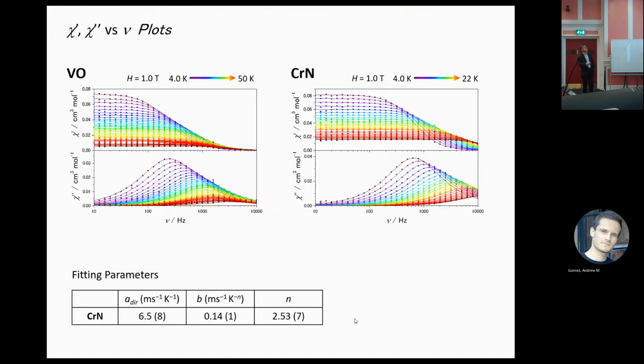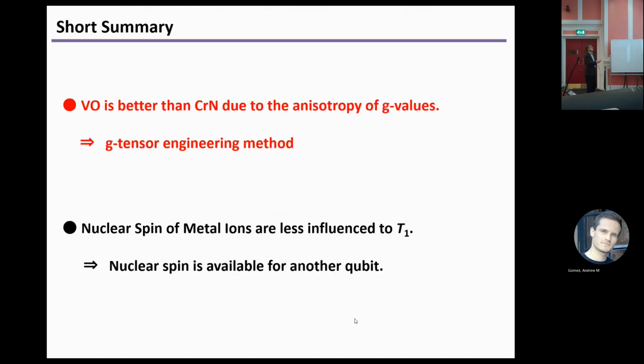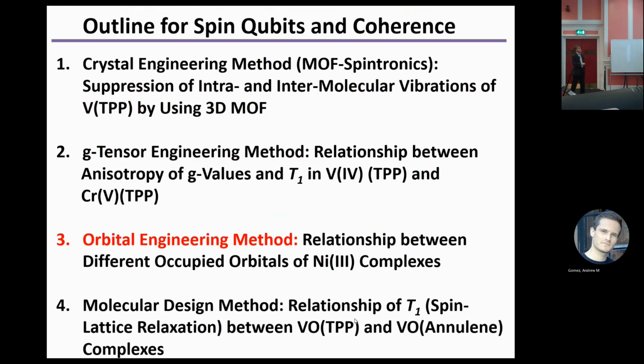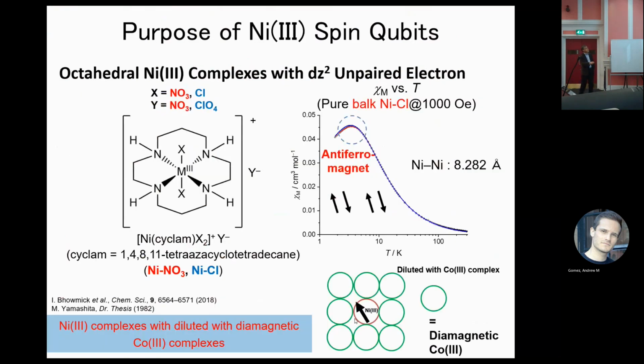So both compounds show a slow magnetic relaxation. This is not a single-molecule magnet, but a phonon bottleneck effect. And oxovanadium is better than chromium nitride due to the smaller g anisotropy. So the third one is the orbital engineering method, the relationship between different occupied orbitals of Ni(III) compounds. Generally, Ni(III) compounds are unstable, but a macrocyclic ligand stabilizes Ni(III), with axial ligand NO3 and counter NO3. This is abbreviated Ni-NO3. Actually, with chloride counter anion, this is abbreviated Ni-Cl.